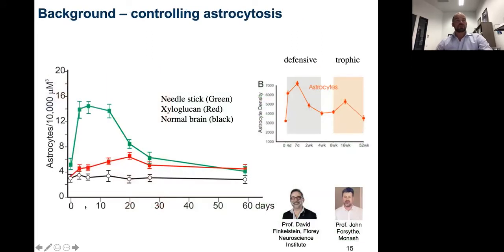As a bit of background, in my PhD years ago, we were looking at the injury response of these astrocytes. You can see where we put a needle stick, in green: you poke the needle into the brain of a rat, and after 3 days you see this activation. You get a lot of proliferation and migration of these astrocytes, which is called reactive astrocytosis. This lasts for about 21 days before it starts to subside back down to homeostatic levels by 60 days.